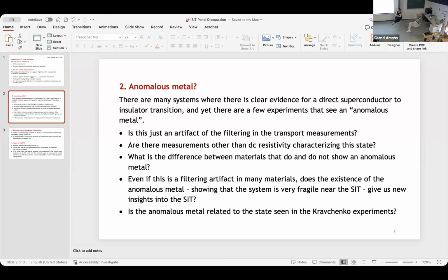So I wonder whether this huge confusion of anomalous metal, which is mostly on disordered systems, where such a composite scenario can exist, is driven by that. For that, you should have a proximity effect, so the resistance should decrease with temperature. Those are matters of detail. Proximity effect has some length scale, depends on disorder, what is the normal metal coherence length, and so on. So it may or may not work to give you a zero resistance. Depends on how thick that is. This proximity may happen at very low temperature. The range is not accessible.